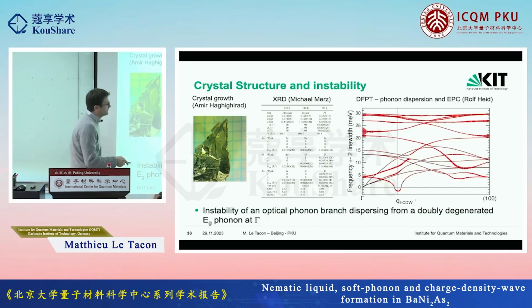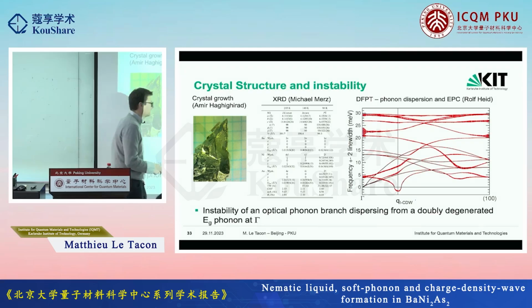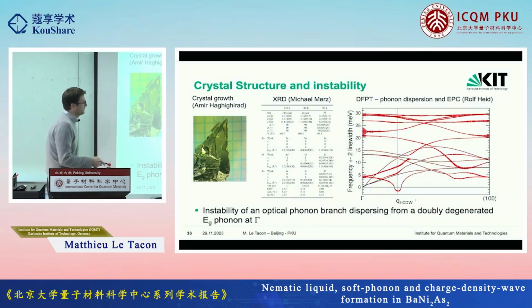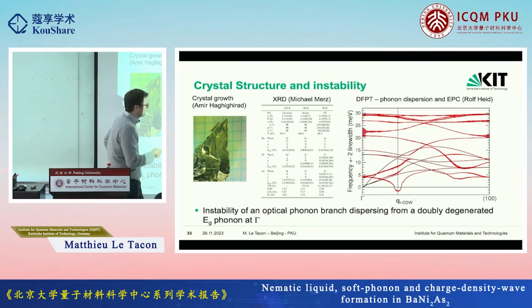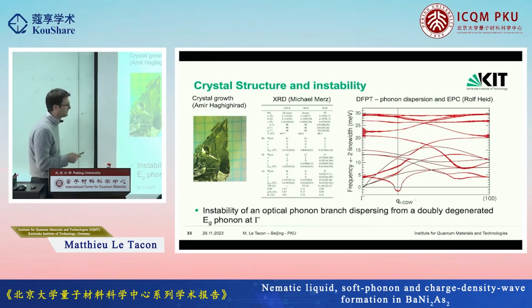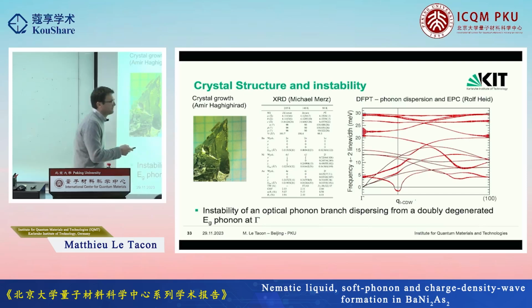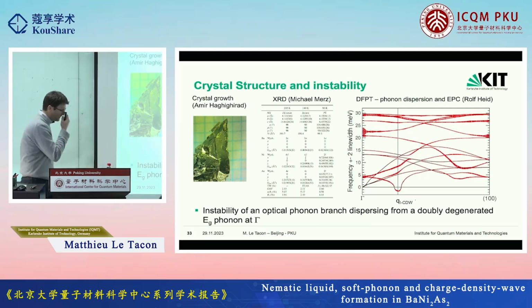So he can calculate the lattice dispersion, and then you can see that now there's a mode which happens to be unstable at a momentum which is quite close to that of the charge density wave. What's interesting, you can also calculate the electron-phonon coupling. You can see that there is a strong electron-phonon coupling for this mode that happens to be the A1g mode that I showed at the beginning, and that actually has a small Fano line shape, for those of you who have the sharp eye of the Raman spectroscopist. So that's where most of the electron-phonon coupling comes from. That being said, this low energy mode, which is the EG phonon, also has some electron-phonon coupling, much smaller. And it happens that this is the same mode that we see split at low frequency that becomes unstable at higher Q. So that's interesting in itself.